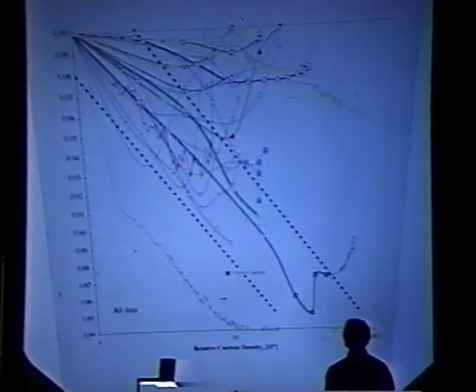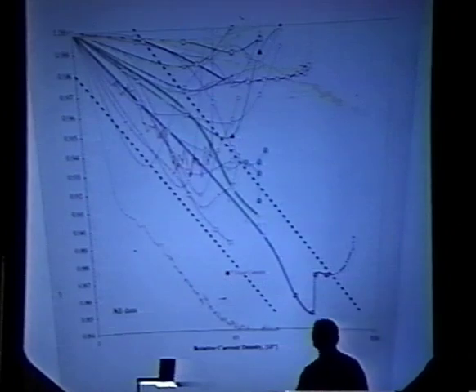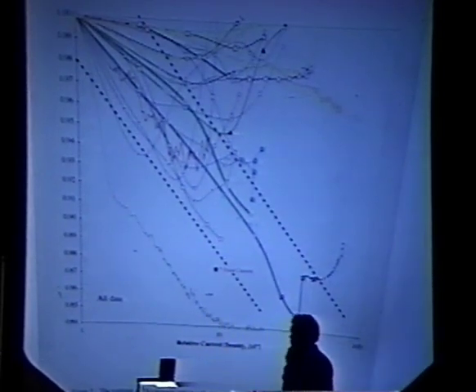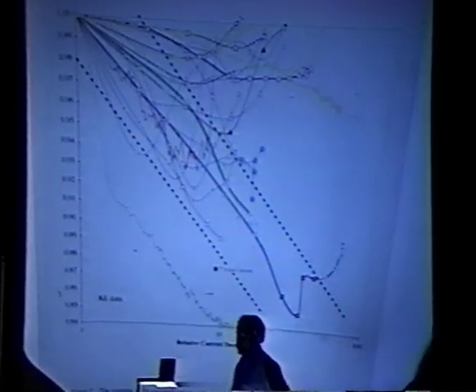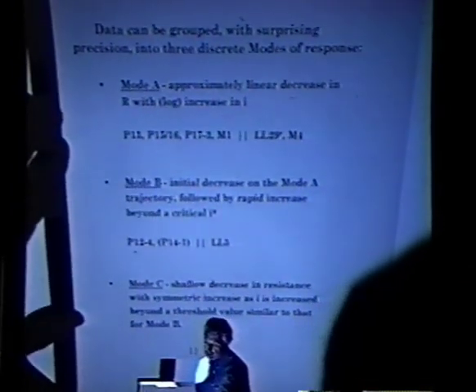If I renormalize the same 26 data sets as I showed you before, according to this method, it certainly looks a little bit better, but you'll notice that I've cheated twice. First, the normalization requires all data to go through this point. And it's a logarithmic plot, which always makes things look better. When you take this into account, you might say, well, this hasn't helped, but in fact it has helped. I submit that the data which are presented on this slide fall into one of 3 different distinct categories of results.